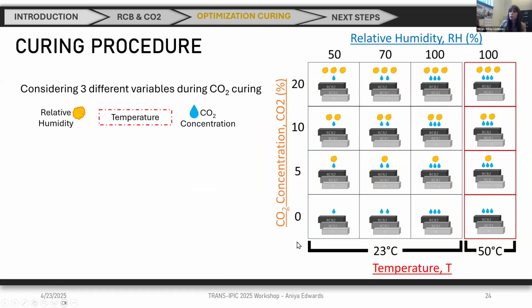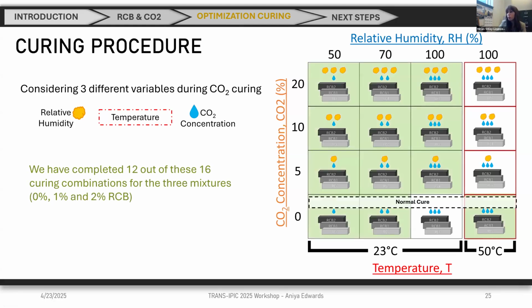So what conditions are we talking about? Okay, so here you can see the matrix. We are talking about no CO2 curing, and 5%, 10%, and 20% CO2 concentration. We are talking also about different relative humidities from 50 to 100, and all of that cured at 23 degrees C. In addition, we want to add also 100% relative humidity and curing at 50 degrees C, because some precast companies use high temperature to speed up the process. We want to compare CO2 curing with no heating versus the one with heating, no CO2.